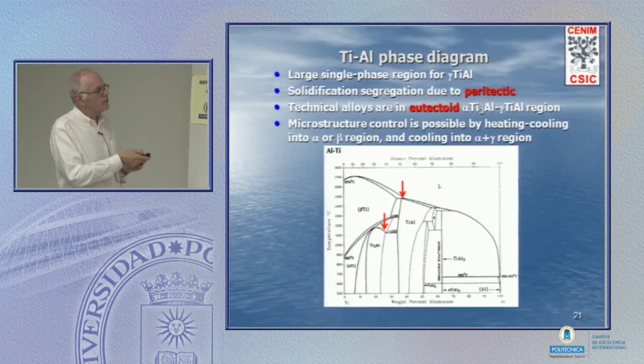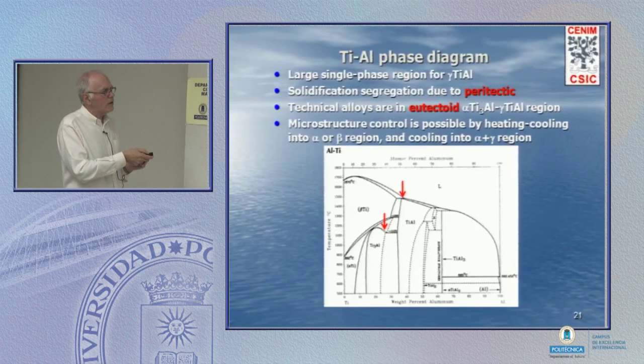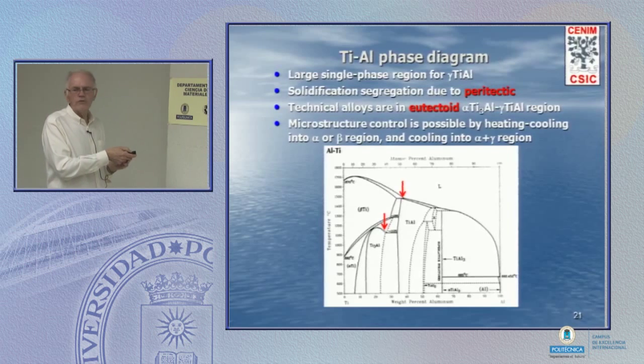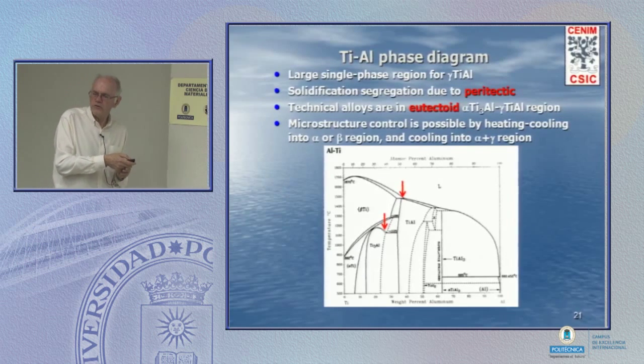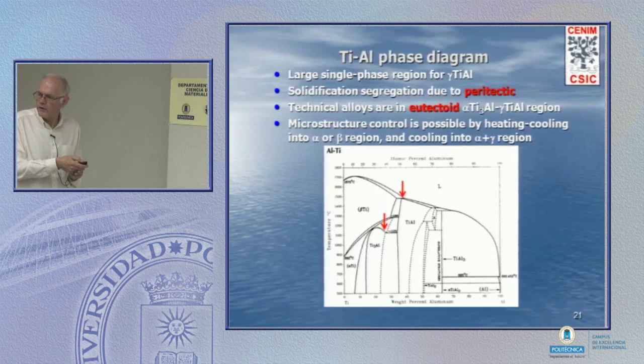Now, one important thing is that if we take that alloy, or take the compound, and melt it down, we run through a peritectic. A peritectic always means that there's a large composition fluctuation. There's lots of segregation inside the alloy, which is very difficult.